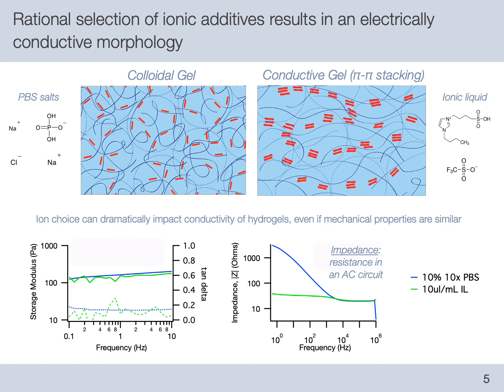Similarly, when we compare PEDOT:PSS hydrogels made with this ionic liquid to ones made with simple salts found in phosphate-buffered saline, we can see that in both cases we can create very soft gel materials with storage moduli around 100 pascals, as shown on the rheological plot in the bottom left here. But the gels made with the ionic liquid possess significantly reduced impedance over all frequencies, as seen on the graph